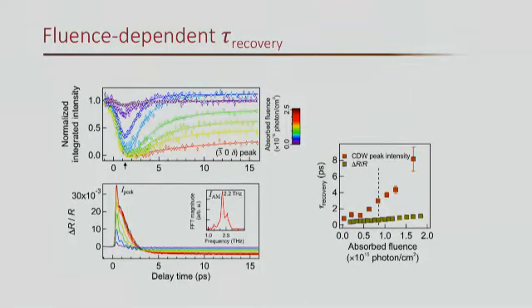And of course, if you compare these two graphs, another striking observation is that if we pump very hard, in terms of ultrafast electron diffraction, the intensity of the peak doesn't recover that fast anymore. So here we fit each curve with phenomenological models that tell us how fast it recovers, say with a single exponential recovery. But in the transient reflectivity measurements, it's really fast. It's summarized in the plot on the right-hand side. The red dots represent the recovery time of the Bragg peak, and the green dots represent the recovery of the transient reflectivity measurement. They behave very differently, especially at large fluence, where one is really fast and one recovers really slowly.